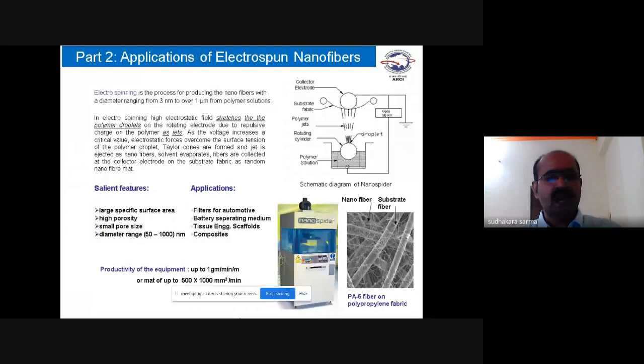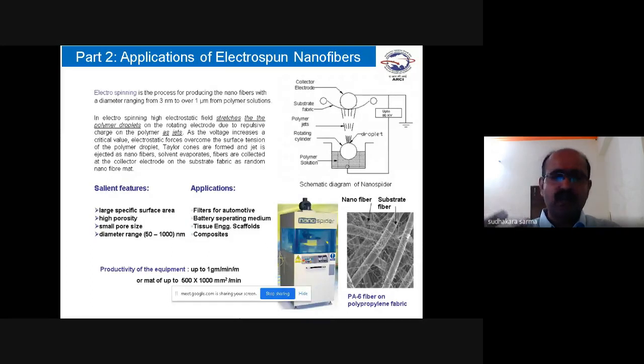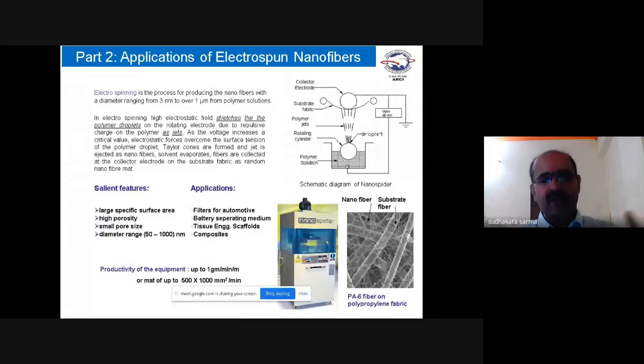The main advantage of these nanofibers is that they have a large surface area. Nano means large surface area, and the nanofiber mat has a high porosity and very small pores, and the diameter of the fiber is 50 nanometers to 1 micron, 1000 nanometers. Applications of these nanofibers are filter applications for automotives, battery applications, some medicinal applications, some composites, even drug delivery. Wide applications are there, and with the Nanospider we can produce a nanofiber mat of size 600 by 1000 mm in 1 minute. So we have a very good production facility at the ARCI.